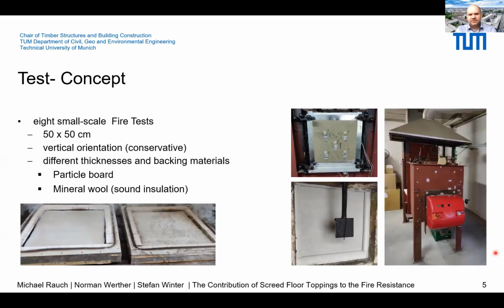The heat transfer through the screeds was measured in a fire test according to the German DIN 4102-8. The temperature in the furnace was measured by plate thermocouples according to the EN 1363. You can see it here on the right picture. And the furnace where we did the tests, you can see here in this picture. And in this picture, you can see the specimen with a dimension of 50 by 50 centimeters, where the heat transfer was measured.